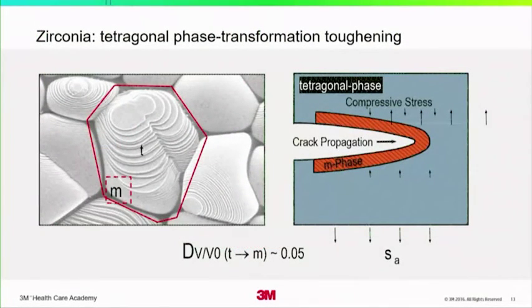Zirconia behaves rather uniquely because as the stabilized form is converted to the tetragonal form, it will change under stress to what's called the monoclinic phase. But when this happens, you get a volumetric change, and it will increase such that when a crack is propagated, the crystal actually changes inside and squeezes down compressively, inhibiting the crack from propagating through the material itself. This is what we call transformation toughening.